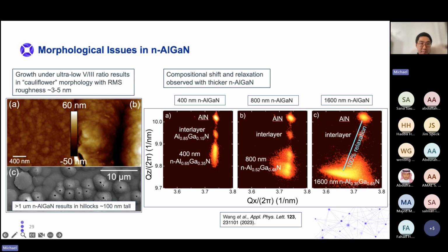Anyways, so we have morphological issues that we observed. The difference between aluminum nitride on silicon carbide versus aluminum nitride on sapphire is that the lattice mismatch between aluminum nitride and sapphire is around 13%, versus the lattice mismatch of aluminum nitride and silicon carbide, which is around 1%. So the defect density is definitely still higher than the aluminum nitride on silicon carbide templates that we were growing before. With this high defect density, what occurs is that as you grow thicker and thicker N-type aluminum gallium nitride,